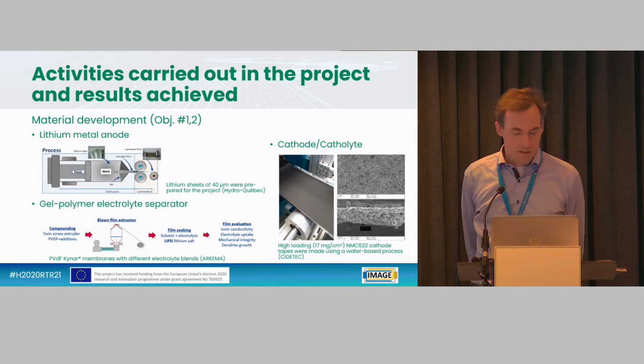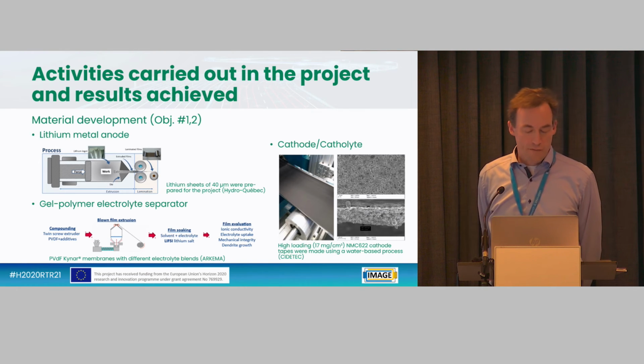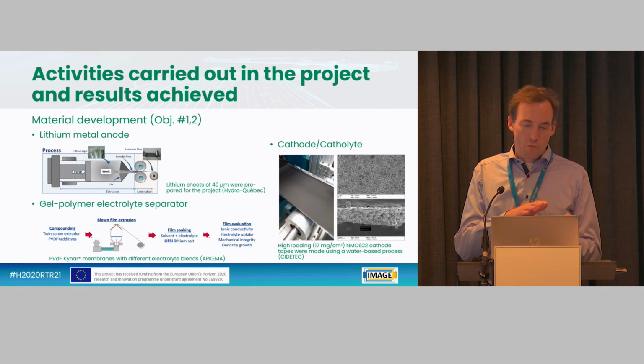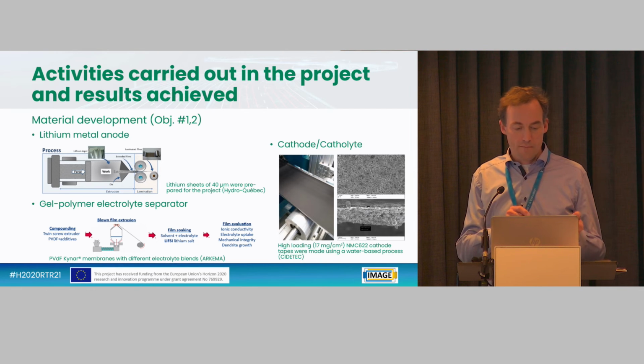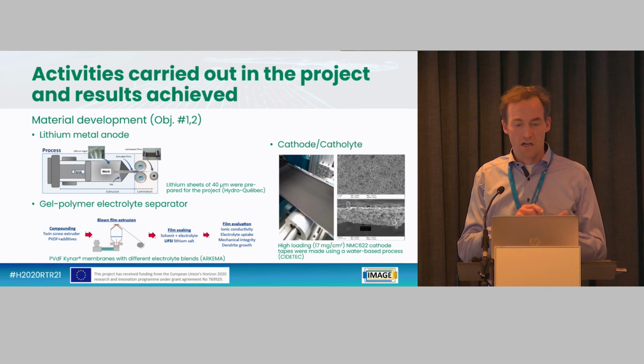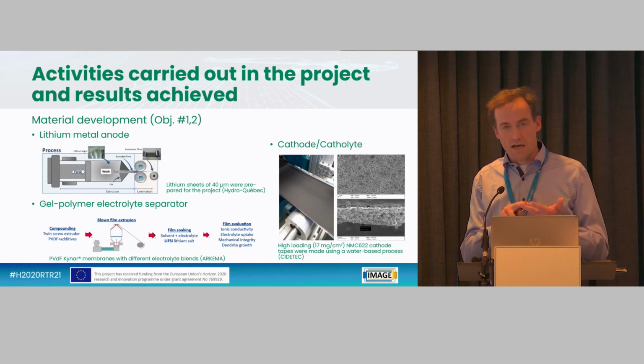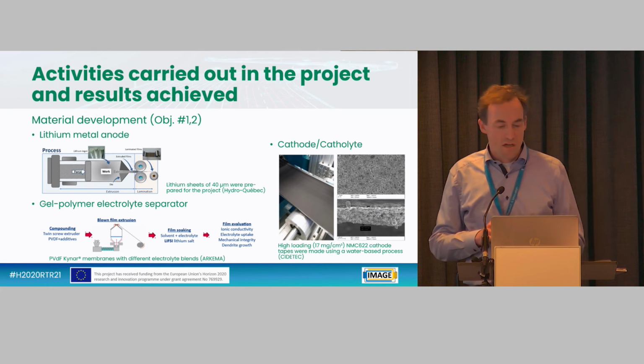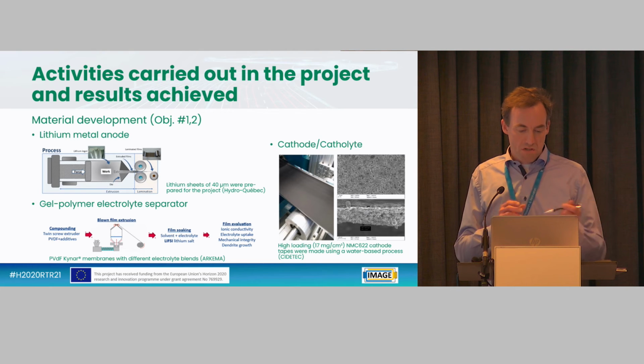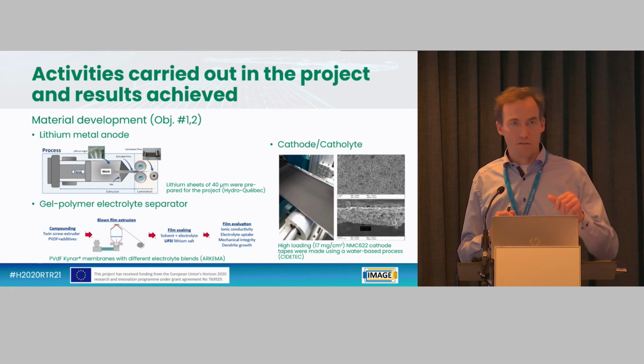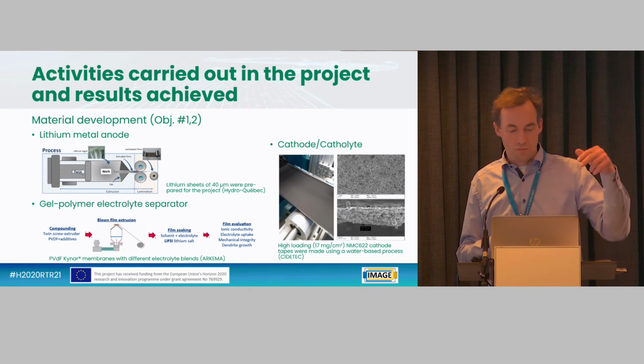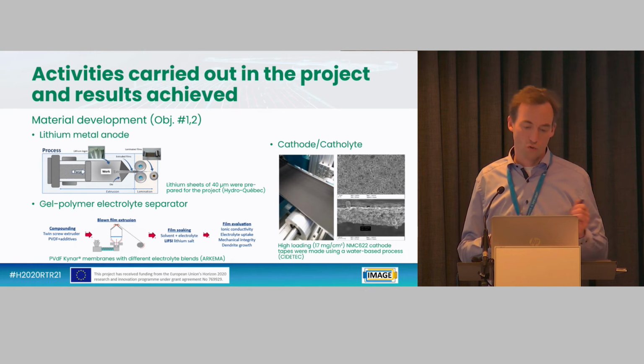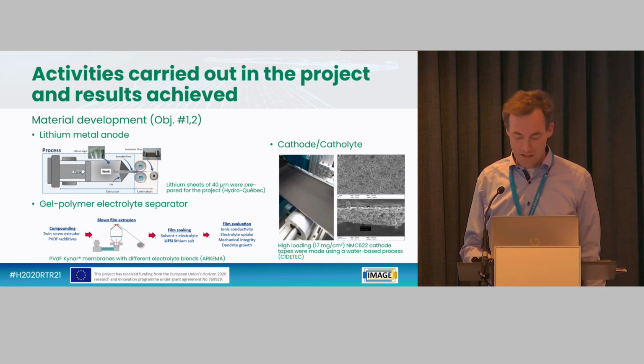Here, Arkema did a big job. You have a material which you combine with an electrolyte, which starts to swell, and you have to make an optimization for mechanical stability, for the swelling properties, and afterwards for the conductivity of the system. So this is at least a 3-factor system, and if you only optimize one of them, the other 2 properties will go down. So this was quite a challenge.